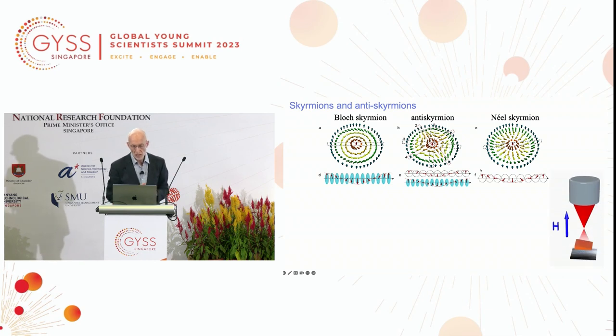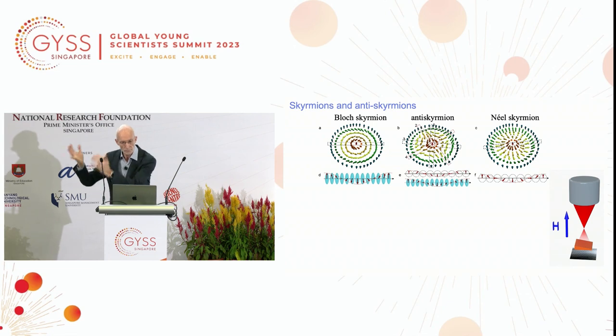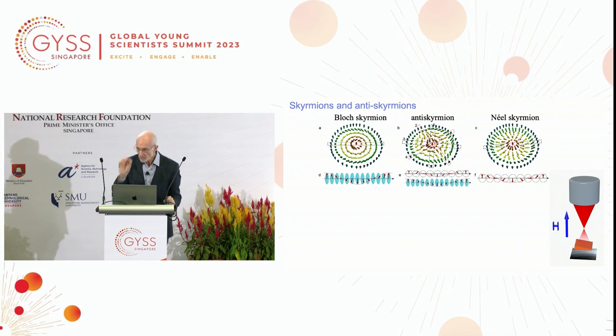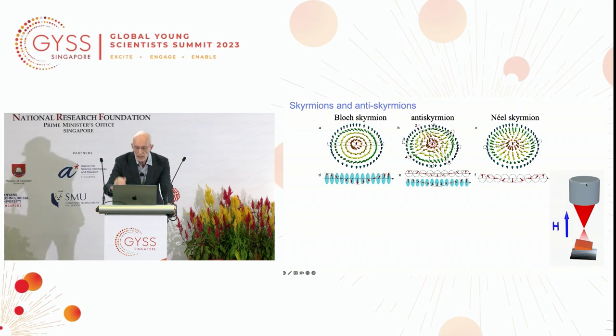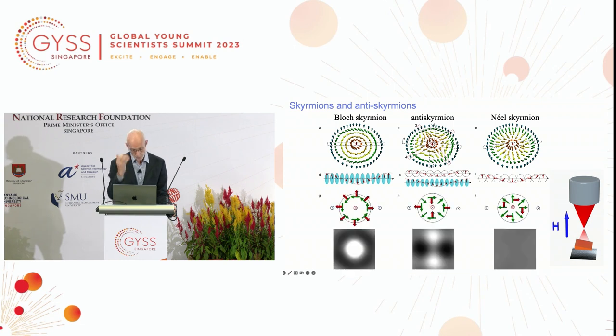And how did we do that? We discovered it by taking a single crystal. Turns out these were made by Claudia, my wife, in Dresden. And we take a very thin layer. We cut a thin layer out using focused ion beam milling techniques, which is electron transparent, less than 200 nanometers thick. We pass this high energy beam, a 300,000 volt electron beam, through that layer, and we detect through Lorentz forces, the same Lorentz forces that give rise to the ordinary Hall effect, we now, the electrons are moved because of forces from in-plane components of the magnetization.